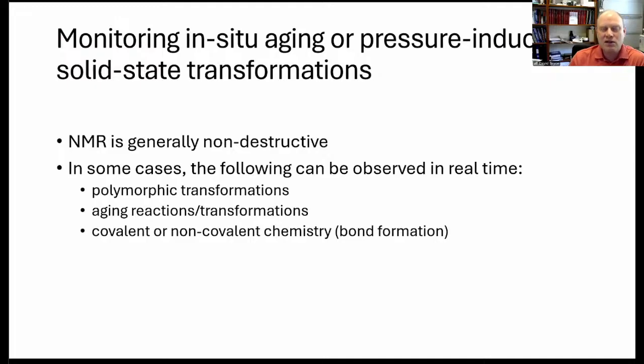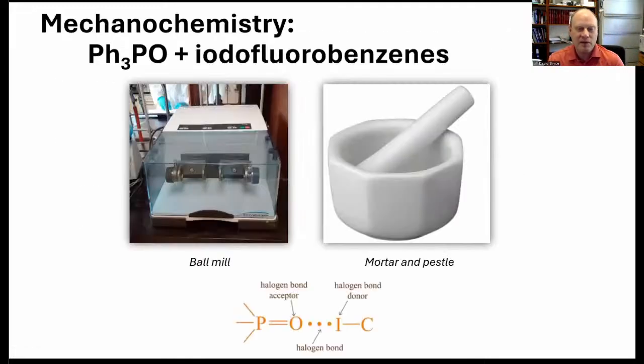In the last little section, I want to look at some in situ aging processes or pressure-induced solid-state transformations. So as I mentioned, NMR is generally non-destructive, but it turns out in some cases, we're able to observe some transformation in real time. So you may have polymorphs that transform as a function of time, either just because of time or the humidity in the air or the temperature or the pressure. So we can look at perhaps polymorphic transformations, aging reactions or transformations, and in favorable cases, maybe some covalent or non-covalent chemistry, which of course we can monitor using other spectroscopic techniques if we have the right setup using mechanochemistry.